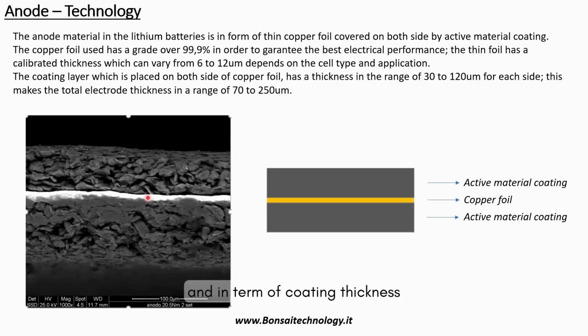And in terms of coating thickness, we're talking about 30 to 120 microns. Okay, so even the anode material at the end becomes very, very thick. So from 70 to over 200 microns in terms of thickness. And the coating material is made of graphite. There are two philosophies. One is to use natural graphite. One is to use synthetic graphite.